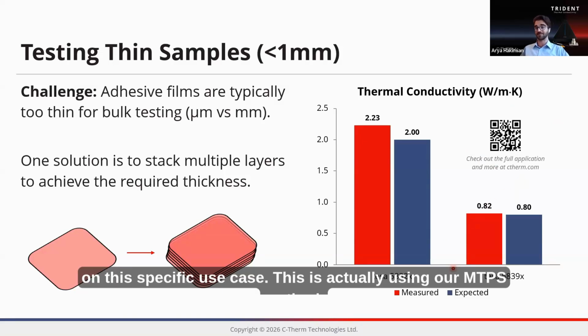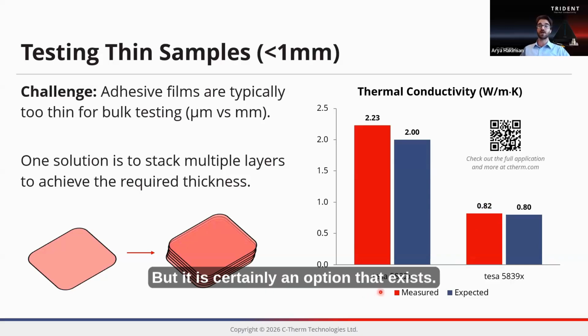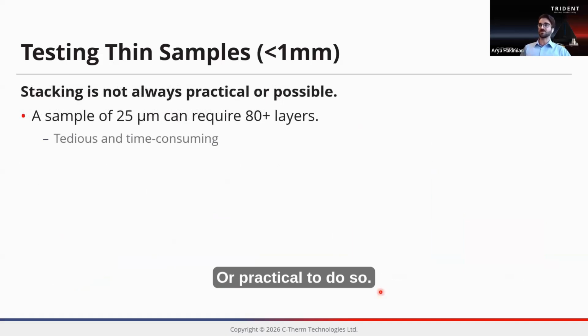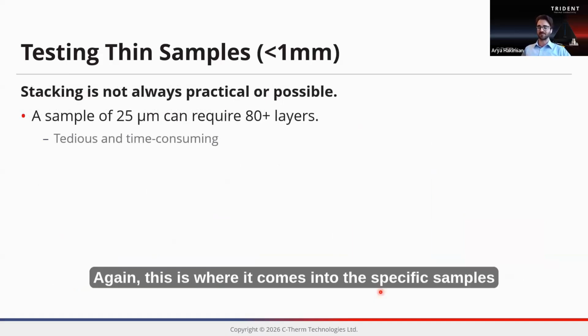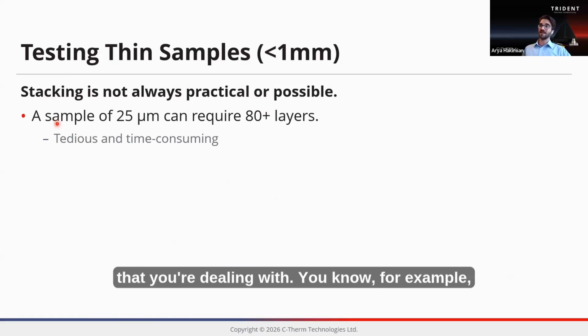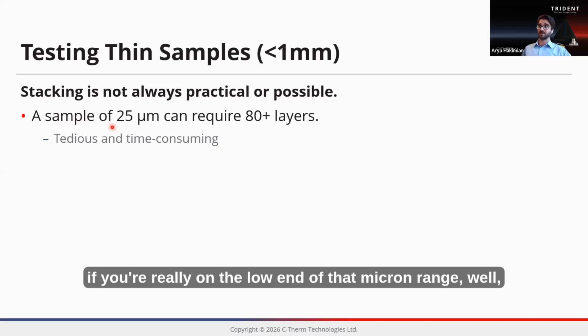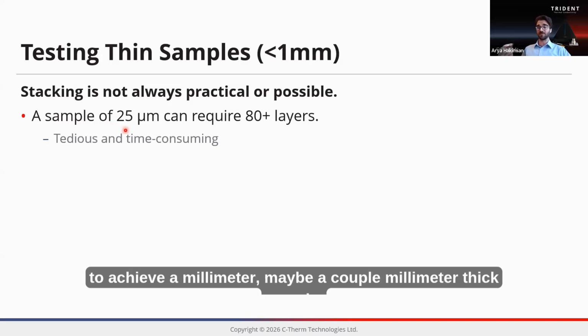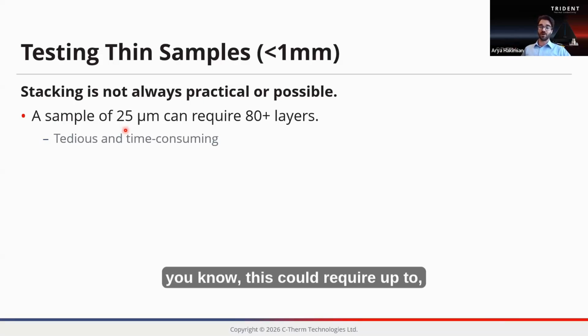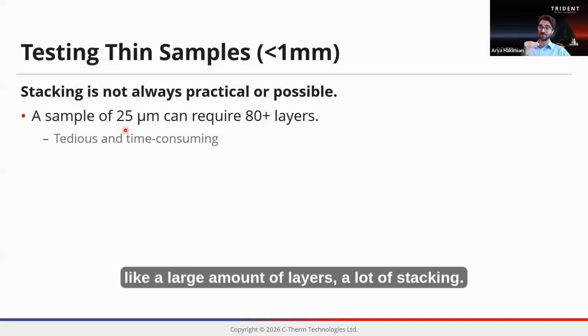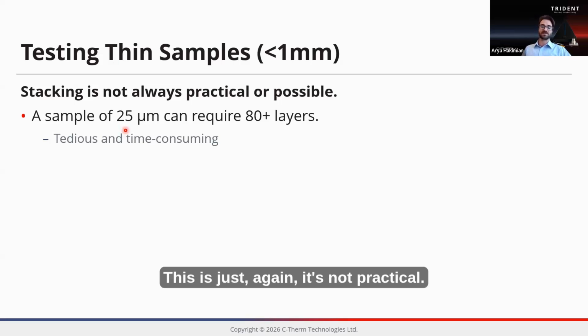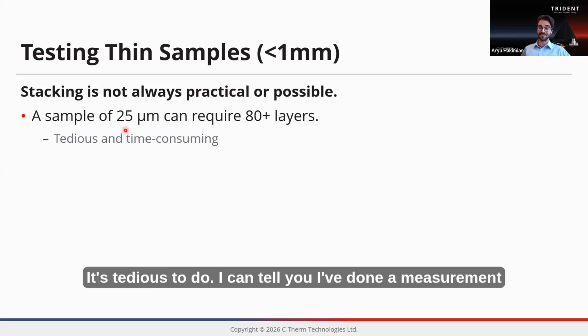This is actually using our MTPS method, but it is certainly an option that exists. But it's not always possible or practical to do so. Again, this is where it comes into the specific samples that you're dealing with. For example, if you're really on the low end of that micron range, well, to achieve a millimeter, maybe a couple millimeter thick sample, this could require up to 80 or even higher, a large amount of layers, a lot of stacking. Again, it's not practical, it's tedious to do.